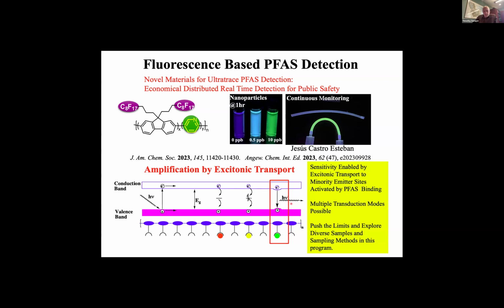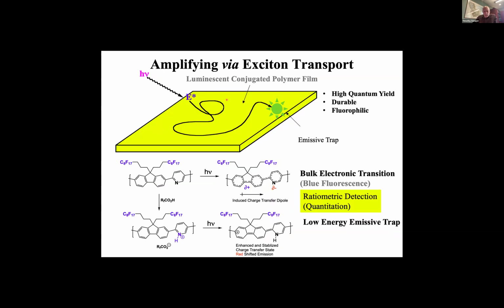What happens here is these excitons essentially migrate throughout the entire system. They migrate through a thin film looking for that one spot that has the PFAS located. We have found in some previous systems that this exciton can sample as many as 20,000 different sites along the polymer. That gives us amplification because it's just wandering around looking for an activated site.